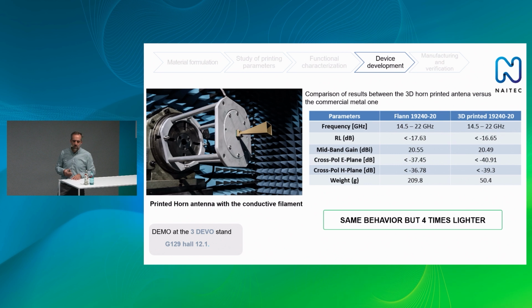And the performance of the printed antenna is actually quite good. Even the antenna people who helped us in this characterization were surprised. They were expecting much more losses due to the plastic and the inhomogeneity and the surface roughness that it might have. But here you can see the results compared to a commercial antenna, the same type, and performance is practically the same. It's really, really good. And the weight is 4 times lower. So that's an important reduction of weight for an antenna that can be important in applications like space or drones or many other applications. This antenna is at the 3D EVO stand in hall 12.1, so you can actually see it.